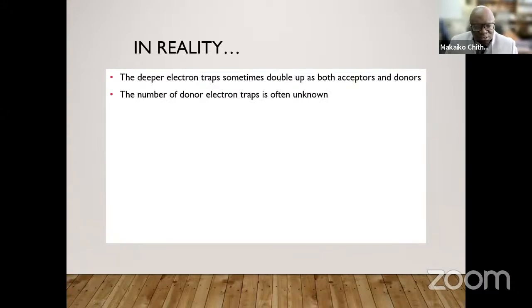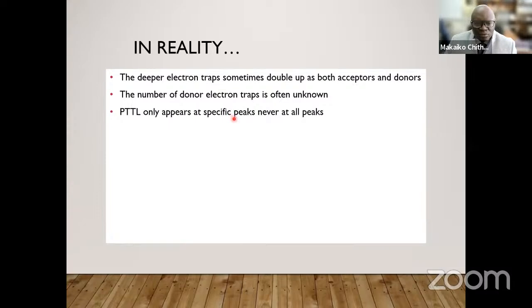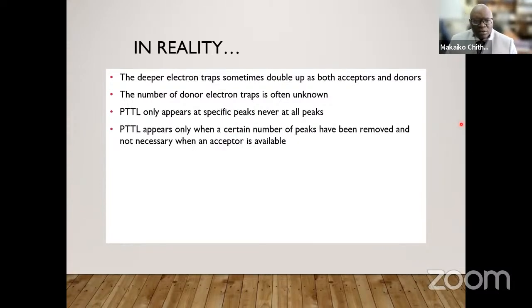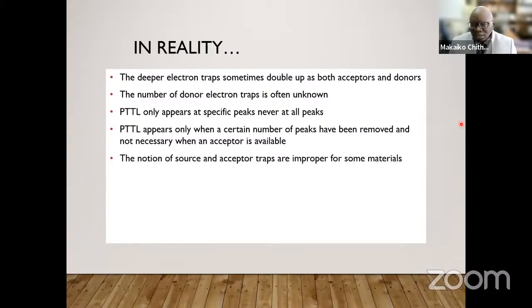So in principle, the number of donor electron traps is unknown. You don't know it. And phototransfer also appears only at specific peaks. It's quite rare to have phototransfer appear at all peaks. Then also phototransfer appears only when you have a certain number of peaks removed. If you think back to the definition, it would imply that once you remove a peak, you can do a phototransfer and actually it will appear at that particular electron trap, but that doesn't always occur. And then the notion of source and acceptor traps is improper for some materials.